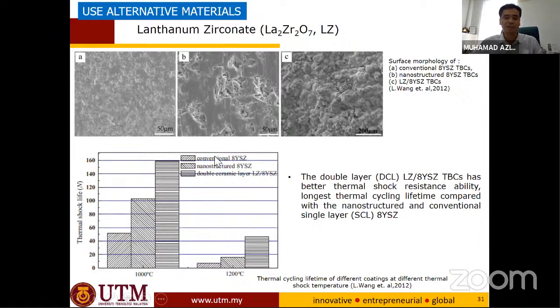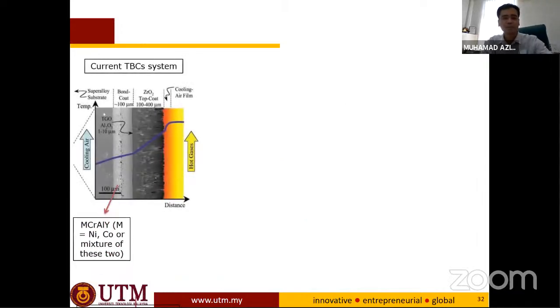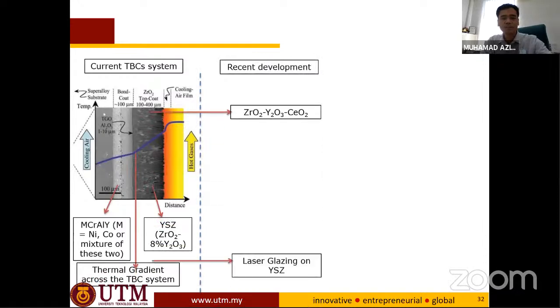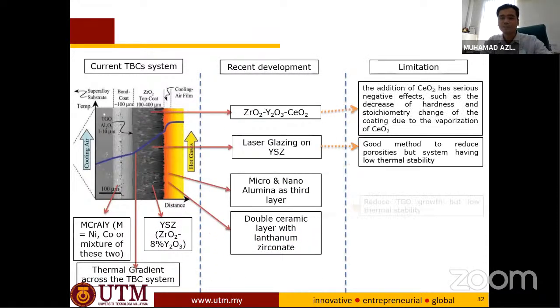But in terms of performance, if you compare the normal YSZ with the hybrid, which we call the double ceramic layer, it can enhance the thermal shock life, for example. Here you can see from the YSZ only, the thermal shock goes up to 160. The same goes at temperature 1200: if you have the double ceramic layer LZ hybrid, it is much better compared to YSZ alone. But the problem is porosity. Of course, we need to cater for this one. So in our research, we have this. So, recent development, we have all these limitations.